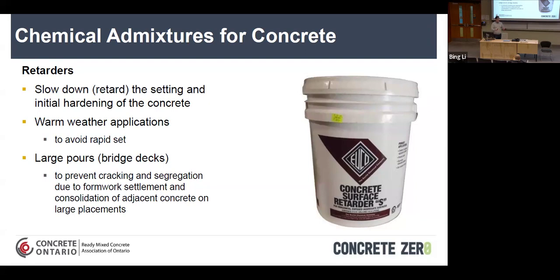And I've actually seen projects where they'll start with a concrete that's expected to retard for 15 hours. And then they'll keep reducing the amount of retarder that goes in so that by the end of it, it all kind of tries to set at the same time. Because we can only deliver concrete at 8-9 meter loads, and you might have a big project that requires 50 meters. You want to try to get it all to set at the same time for whatever reason the project requires. So that happens too.